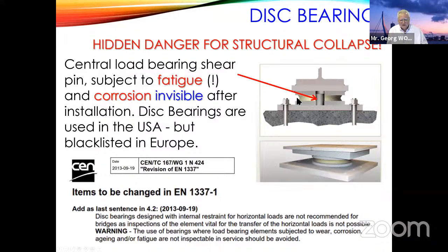You see, this is always covered, it's invisible. And this was the reason in Europe this bearing was never used. And the European bearing standard EN 1337 is now in revision since some time, as you see here, this is from 2013. And in the new version, there will be a warning where they say these bearings designed with internal restraint for horizontal loads are not recommended for bridges, as inspection of the element vital for the transfer of the horizontal load is not possible. The use of bearings where load-bearing elements subject to wear, corrosion, aging, or fatigue are not inspectable in service should be avoided. This is really, I think, the only really dangerous bearing.